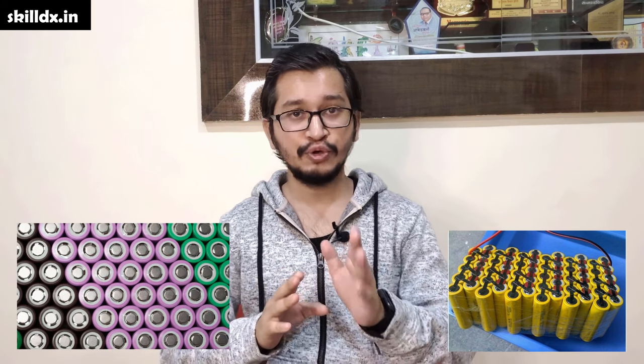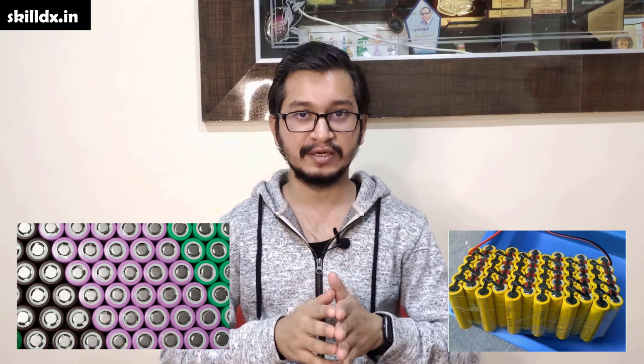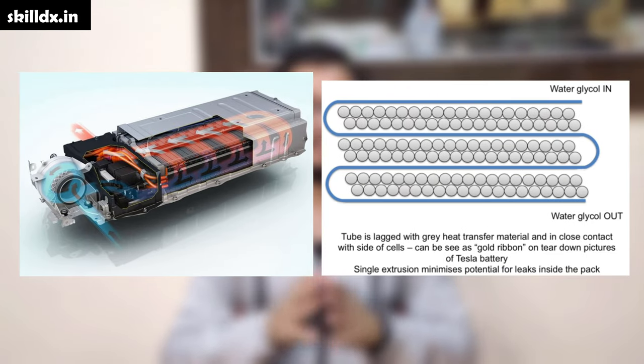Historically, cylindrical cells have been very popular because they are the easiest to manufacture, and they are still the cell of choice in Tesla automobiles. But when you try to pack cylindrical cells together to make a battery pack, quite a lot of space is wasted between the cylinders. If we design our battery pack so that the space provides a pathway for coolant such as forced air or forced liquid, that can be an advantage, but often there is more space left between the cells than is actually needed to cool the battery pack. So prismatic cells are a little better in that respect.